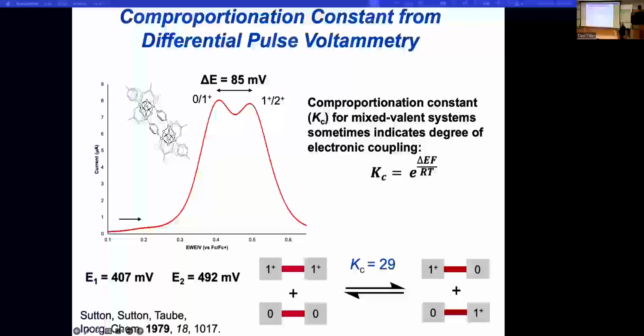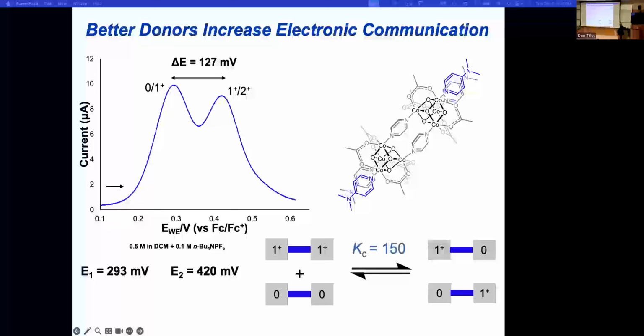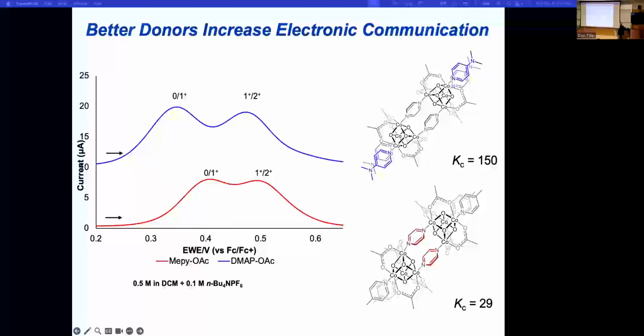This is something you can interrogate by looking at Sutton and Taube's theory, which indicates that you can take this electrochemical data and convert it to a comproportionation. So that indicates the equilibrium between the monooxidized state and the doubly oxidized state, as indicated here. And what this is saying is that the equilibrium constant is pretty low. But how can we tune that? What we found is that if we increase the donor strength of the ligands on the cubes, then that equilibrium constant increases. So we know how to change that comproportionation constant.